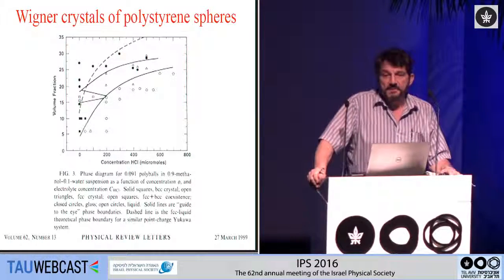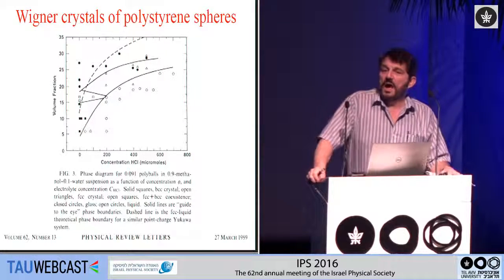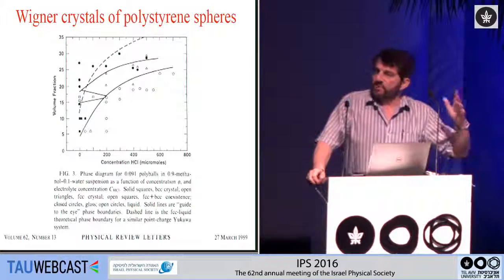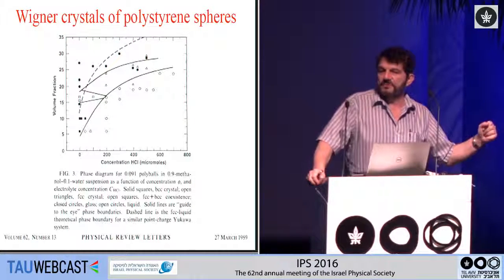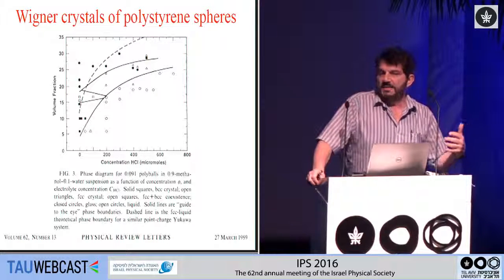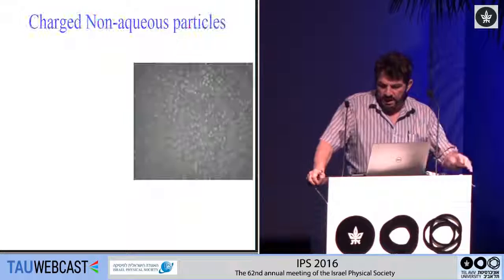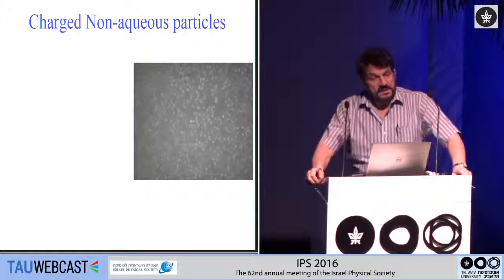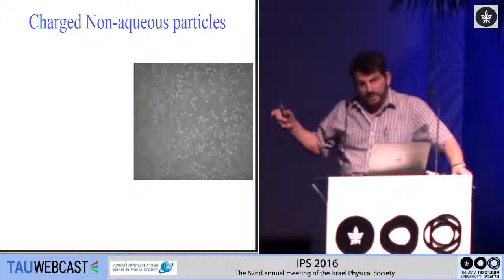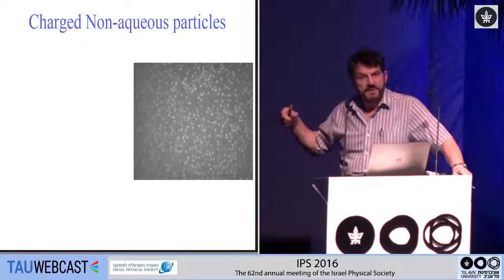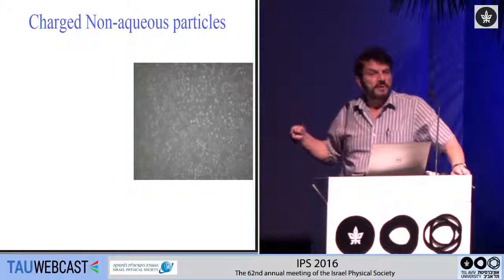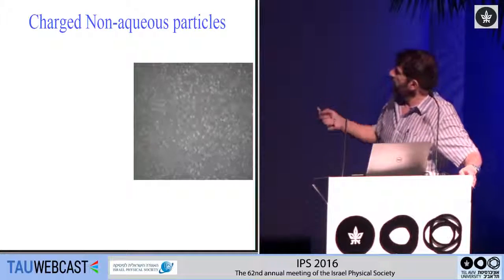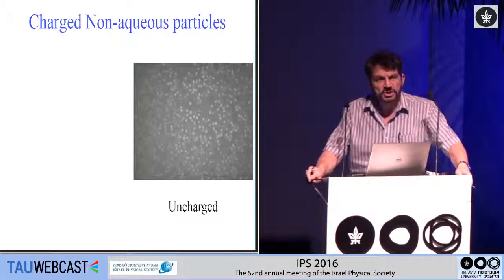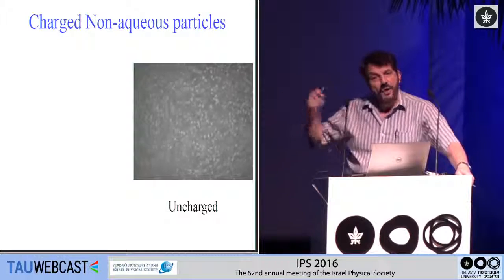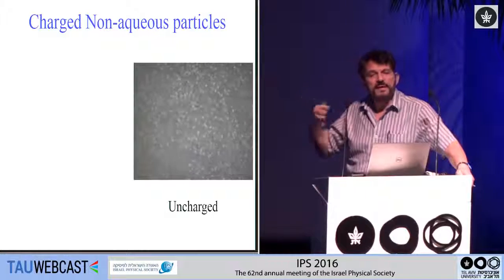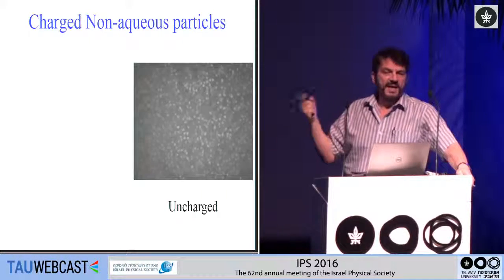So we set out to try and mimic this behavior, but we didn't want to use the aqueous system, which has a very high dielectric constant and therefore very short length scales, using charge as the means for repulsion. So instead we used a non-aqueous system, where, because it's in an oil, the dielectric constant is much lower, the length scales become much larger, and you can use confocal microscopy to actually view the particles. And here is the way the particles look. In this case, they're not charged, and so you can see they are randomly situated. They can occur at any positions relative to their neighbors, except, of course, they can't overlap.